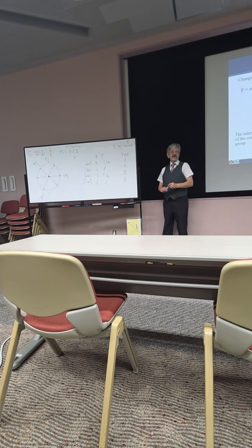Again, I have 2. But now the direction along which the electric field can develop is perpendicular to the direction of compression. You see, here is the two-fold axis that remains. Again, I can have an electric field, but now instead of being along the compression, it is along the direction that is perpendicular to the compression. Pretty simple, isn't it? Once you get the idea.